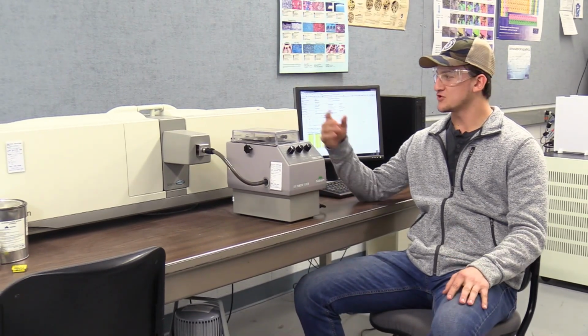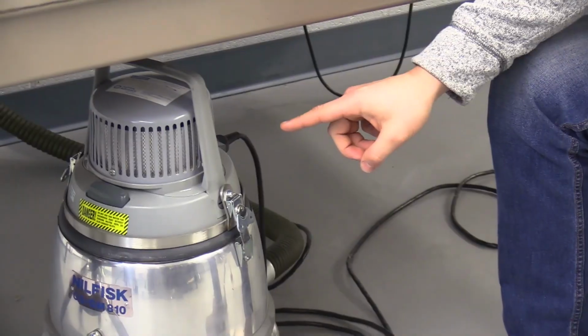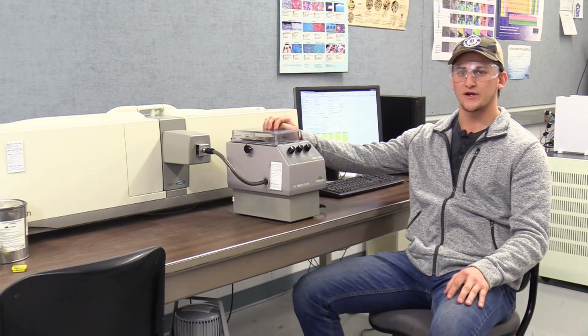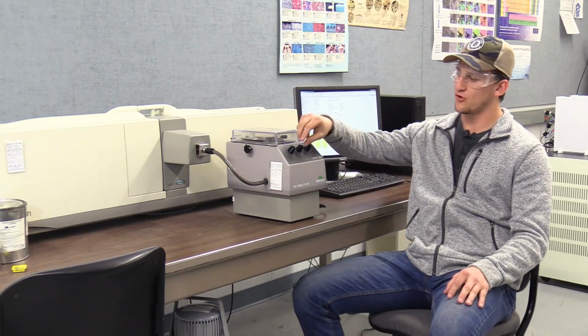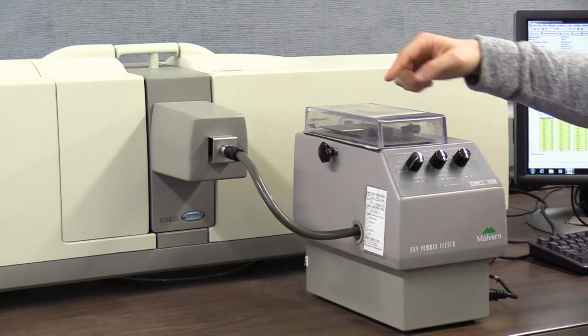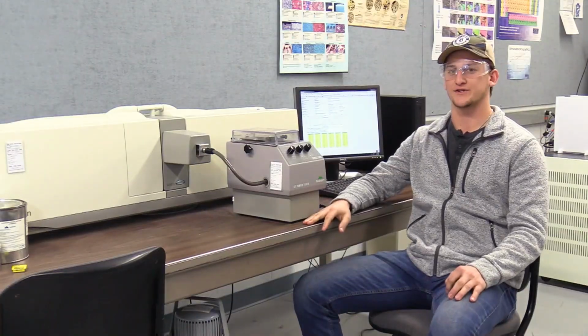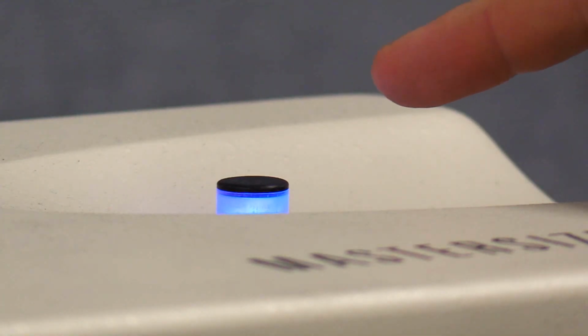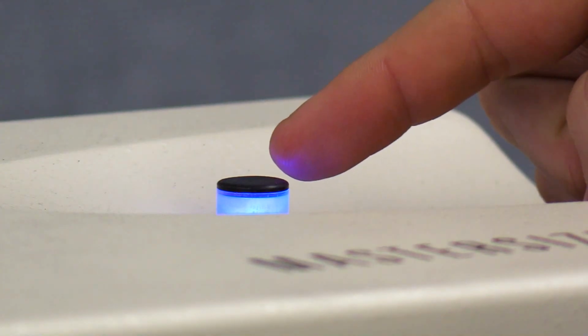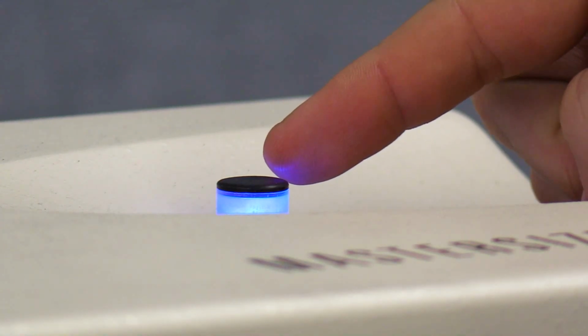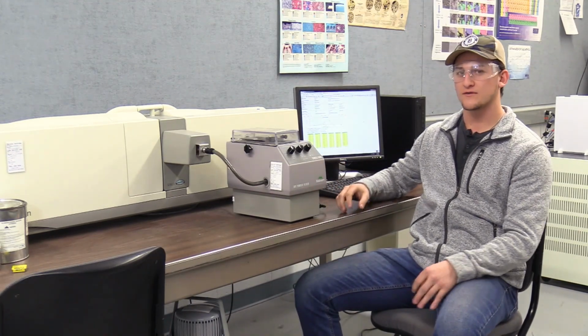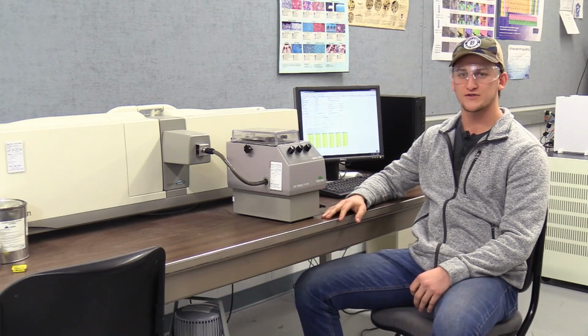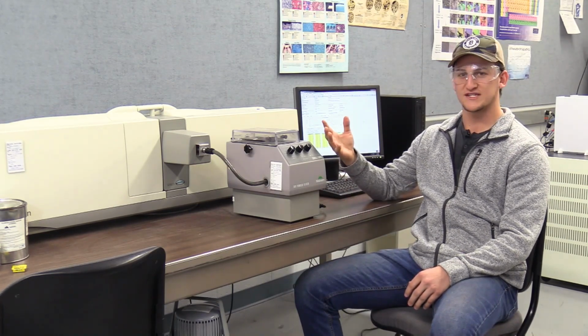What we do with this machine here, called the Mastersizer, is it gives you the particle size distribution. It pulls a vacuum, and you put your powder in the top here, and it sucks the powder down through as you pull on your feedstock here. It'll suck through the tube and then go into the Mastersizer. There's a blue laser that shoots across as the powder flows through. That powder is then measured using the refractive index of the blue laser. After all of the powder goes through the feedstock, it shows up here on the computer, and it'll give you a particle size distribution of what you just tested.